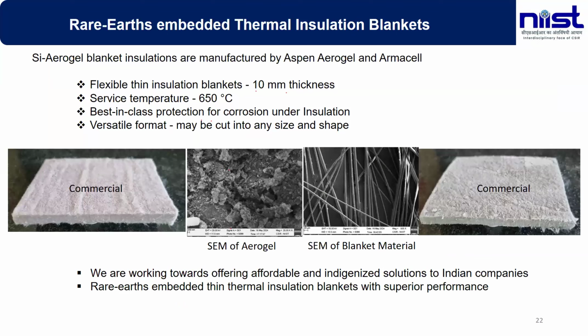So this is also showing commercial aerogel blankets which are used for insulation application, and they're all commercial only. We found that some of them are calcium silicate, and as far as high temperature is concerned, calcium silicate won't work. And my purpose is to find refractories for 1800 to 2200 degrees Celsius.